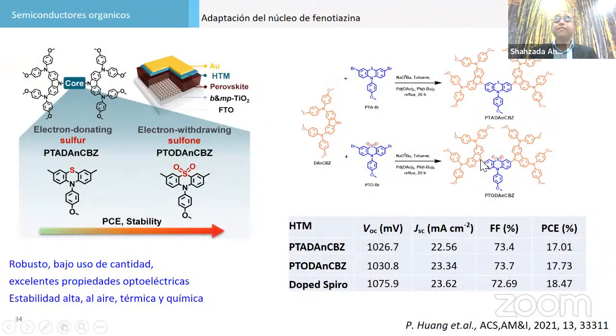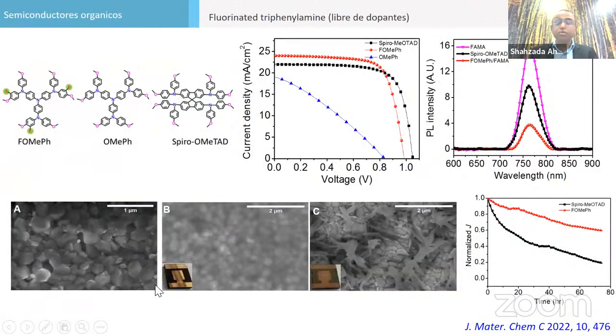Similarly, we took another core, phenothiazine. The phenothiazine core is very low cost, and it's more robust. It's a very simple process. We use a one-step process to synthesize this phenothiazine core. It was more air and thermally stable. It's robust and has very good optoelectrical properties. This is the phenothiazine core. So we use different types of organic semiconductors to increase performance.